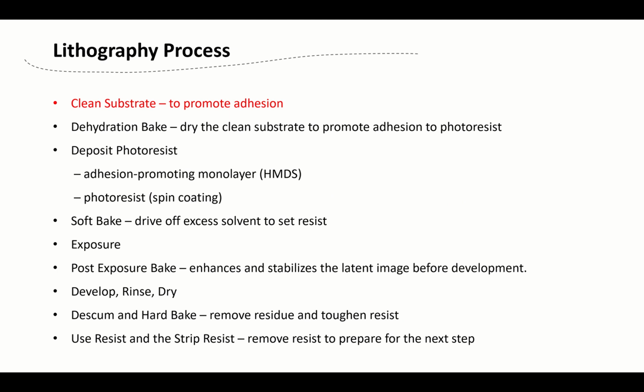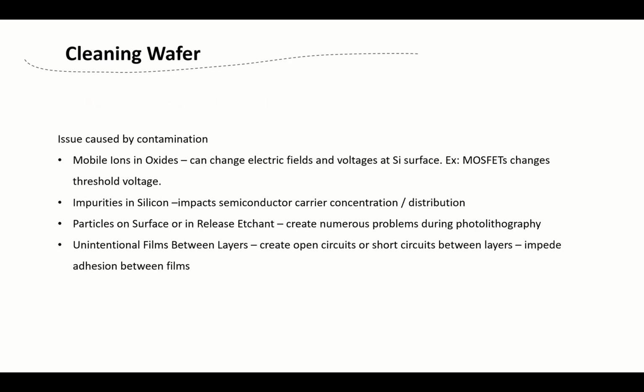First is cleaning the substrate to promote adhesion. For cleaning the wafers, why do we want to clean the wafers? First, if there are contaminations, they will affect the mobile ions in the oxide. If there is a mobile ion in the oxide, it will change the electrical field and voltage at the silicon surface, which will affect the MOSFET threshold voltage. And if there's an impurity in the silicon, it will impact semiconductor carrier concentrations and distributions.